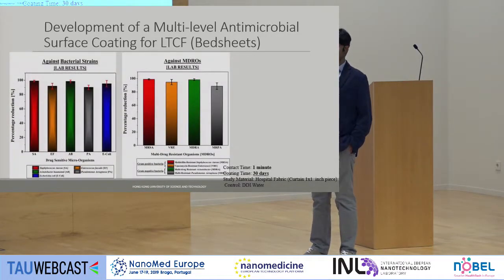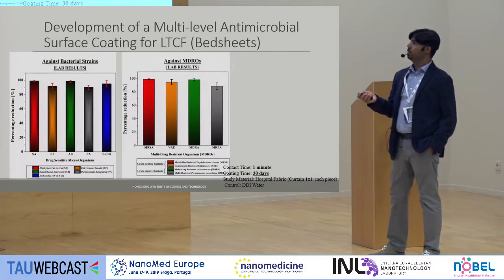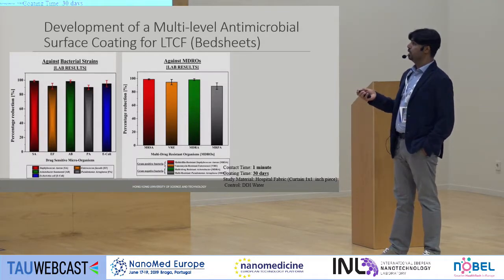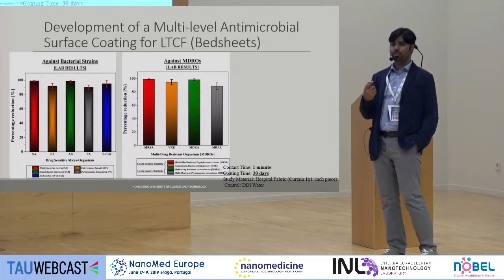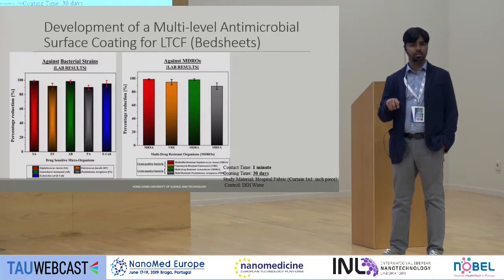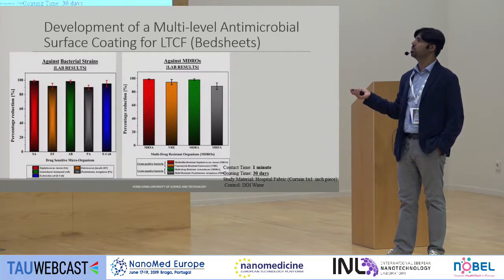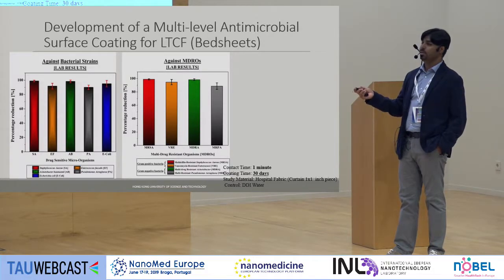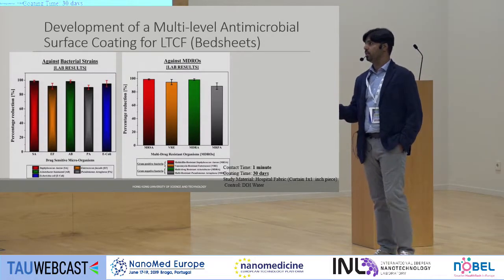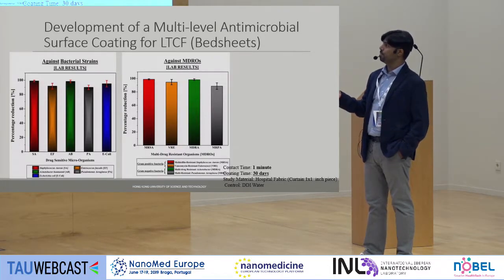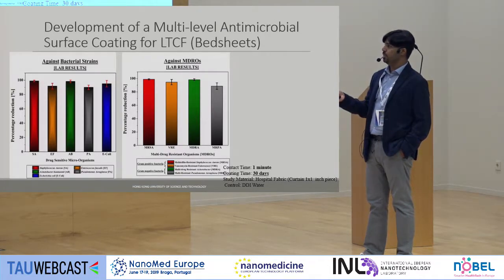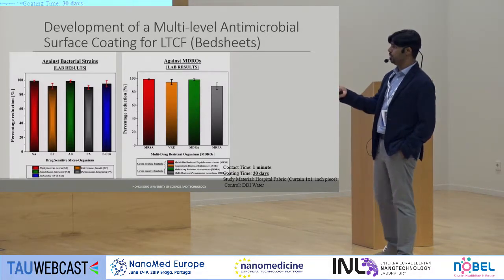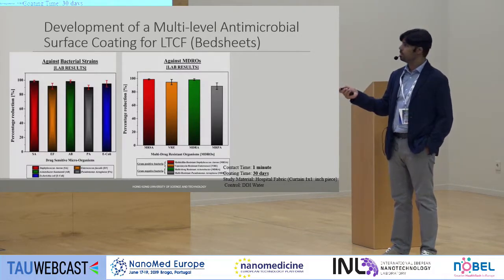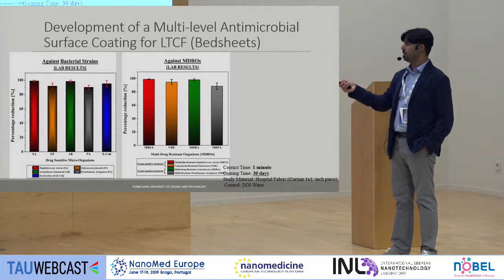So in the lab, in the control environment, the test we have done, I'm just giving you a summary, that we give a challenge time of 1 minute. So we wanted to see if the bacteria are going to die with this polymeric technology in 1 minute. So we found around 99% of bacterial cells were dying. Here are some bacterial strains that are drug sensitive, like Staphylococcus aureus, Enterococci, and Pseudomonas, E. coli. But I also checked some drug resistant strains like MRSA, VRE, drug resistant Acinetobacter, and Pseudomonas.